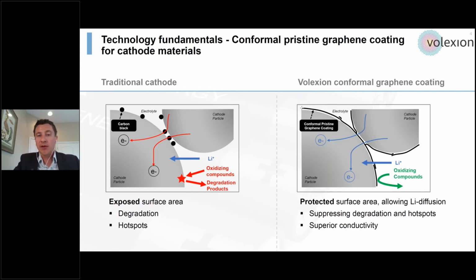On the right-hand side is how Volexion does things differently. We apply our pristine conformal graphene coating to commercially available cathode particles, and it essentially shrink wraps around the cathode particles a few layered graphene layer that allows the lithium to flow in and out of the coating, which is a desired property for our application, but blocks everything else from having access to the cathode particle surface, which leads to the suppression of degradation and hotspots. And also, graphene is one of the most conductive materials ever discovered, which is a desired property for lithium-ion batteries.